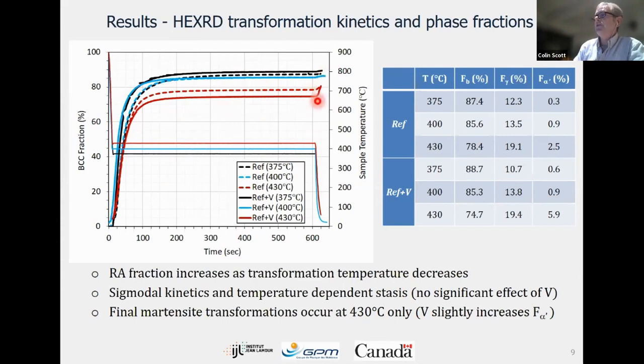But there is a difference. If you look at the higher temperatures, you can see at this point here, where you get into the cooling stage, this is martensite forming. It's not bainitic ferrite, this is martensite. So we end up with the same amount of retained austenite, but we have a little bit more martensite when we add vanadium at the higher temperature.